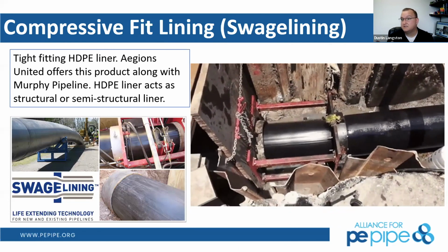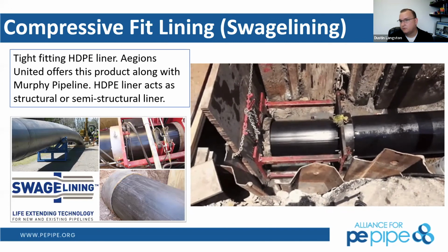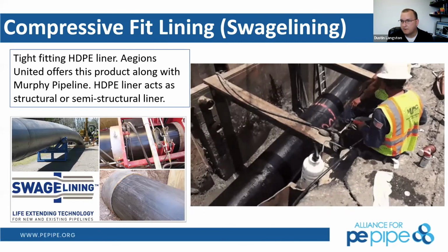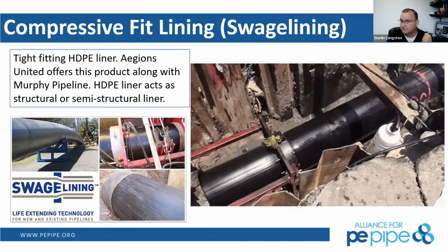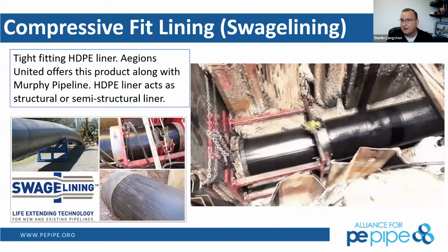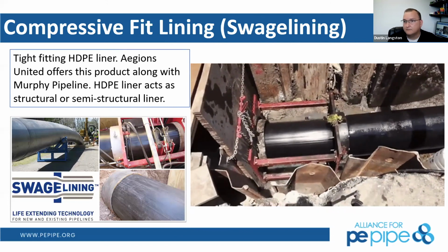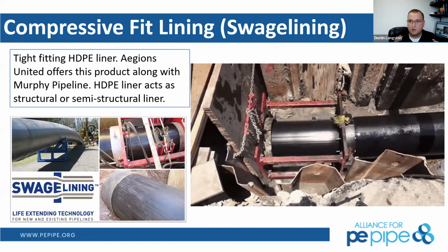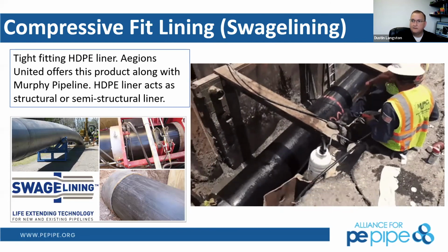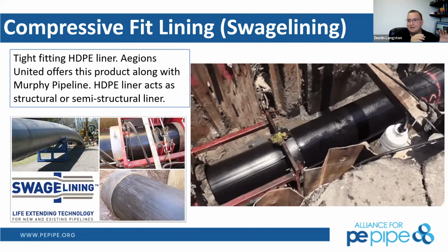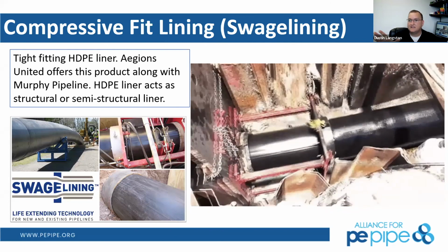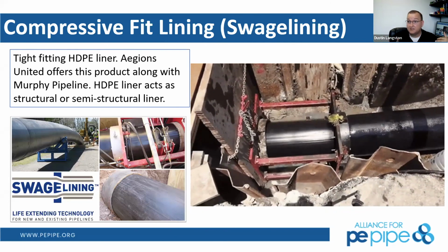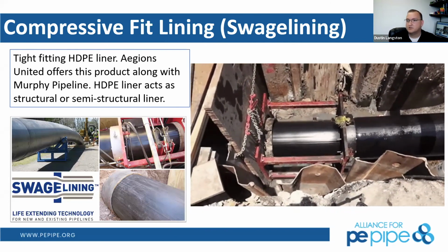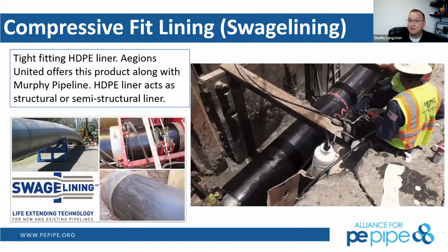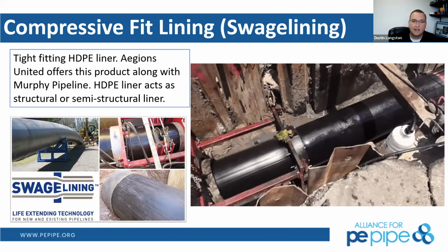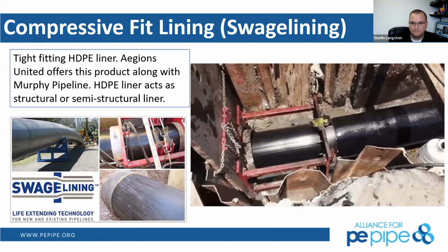It's going to reduce the diameter of the pipe down to, let's call it, 2 inches smaller than the host pipe. And while we do that, we hold a tension on the pipe that doesn't allow it to go back to its original diameter. And by doing that, we now have a smaller diameter that we can slip down the host pipe. And by the time it gets to the other end, we now release the tension on it, and it'll go back to its original diameter, or attempt to, and become a snug, tight-fitting liner against the host pipe.